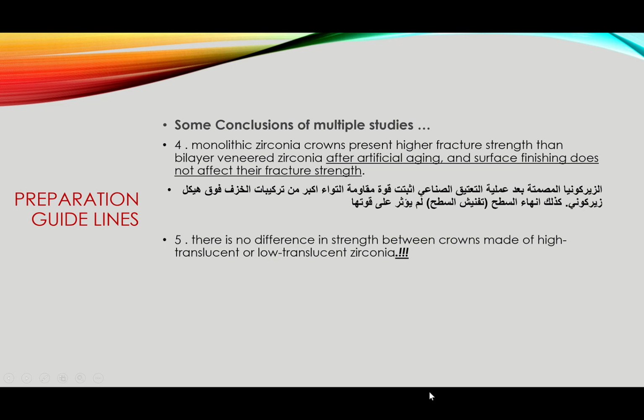All right. There is no difference in strength between crowns made of high translucent or low translucent zirconia. This is a conclusion of a study too, and I put it up to go against it. Of course, there is a big difference in strength between high translucent and low translucent zirconia. They probably ran this study on specimens that have different translucencies but close to each other, in the same range, like in the 4 yttrium stabilized zirconia range or the 5 yttrium stabilized zirconia range. And then they came up with no difference between two different products in the same range but with a little bit different translucency, because it doesn't make any sense.